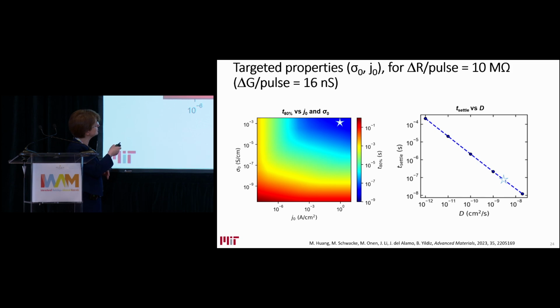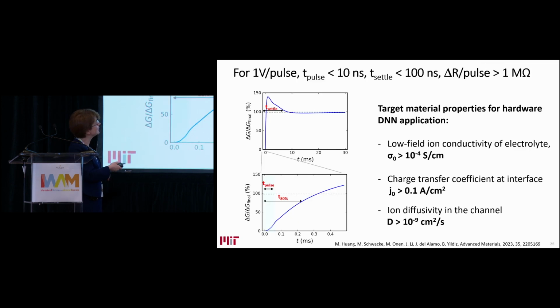And that's the star here. So if we summarize the found properties, we see that the electrolyte for any ion that you want to work with should have conductivity more than 0.1 millisiemens per centimeter. The charge transfer coefficient or exchange current density should be greater than 0.1 amp per square centimeter. And the ion diffusivity in the channel should be greater than 10⁻⁹ square centimeter per second, so that we can program with nanoseconds and with 1 volt.